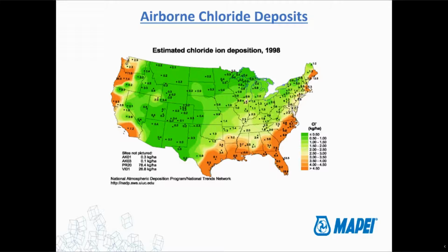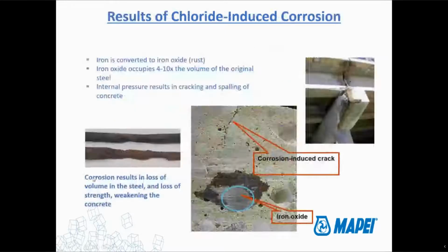As you can see, the difference out there is it's very dry. I mentioned that humidity has a big part to play in corrosion, and the humidity in California is just very low. It's very dry and pleasant out there. Same with Washington and Oregon. So you just don't see as much of the corrosion actually happening simply because of the environmental conditions. It's just not ripe for corrosion in those areas, so we don't generally see as much of a problem as you do on the East Coast. But the end result is the same, no matter where you are, once chlorides start to infiltrate your concrete.